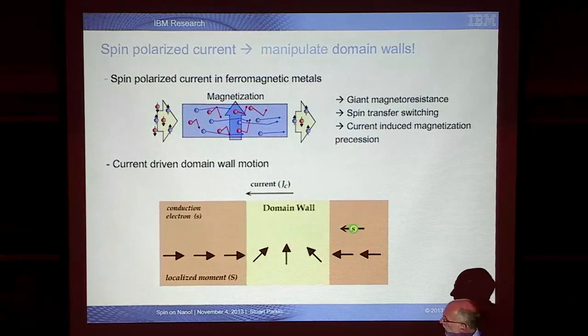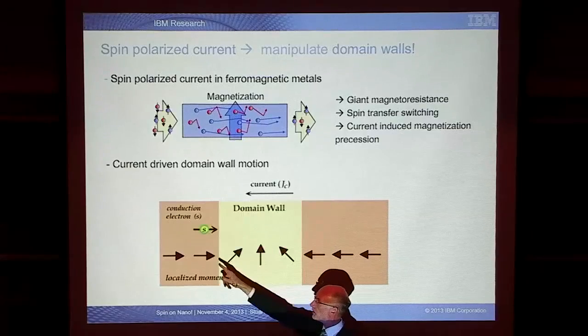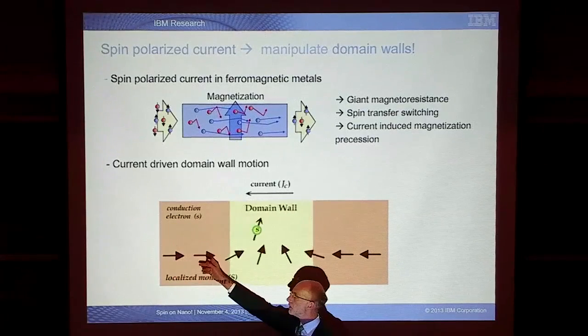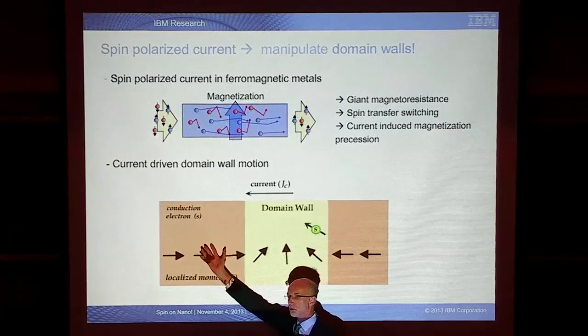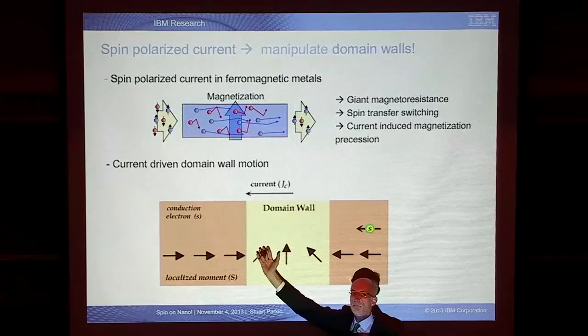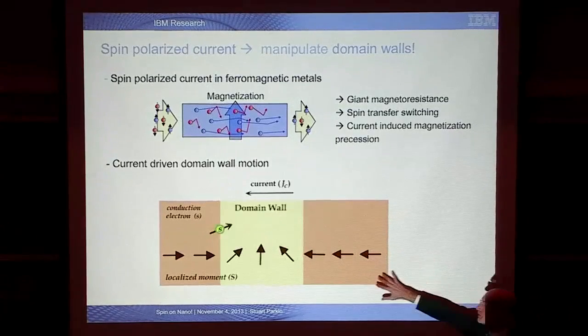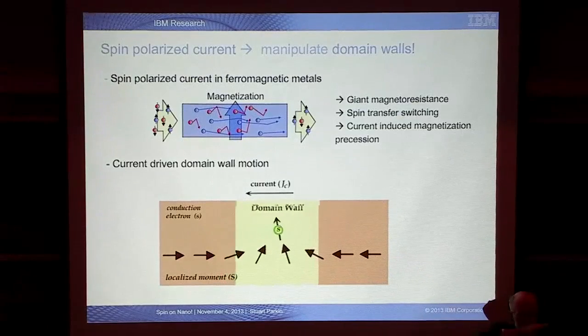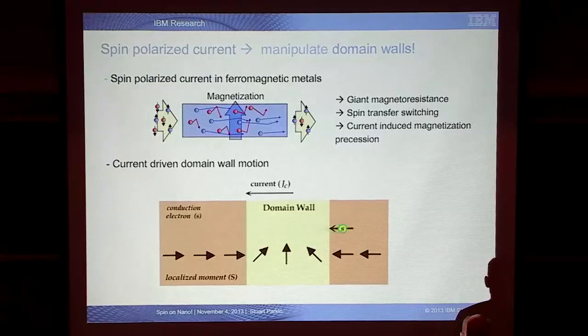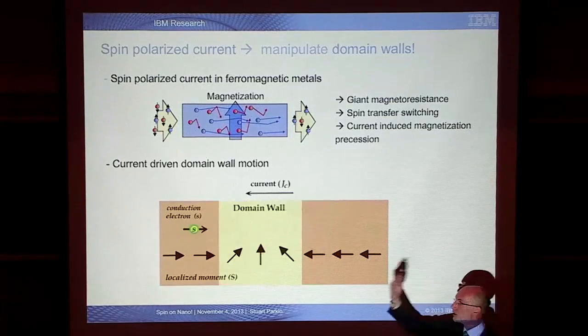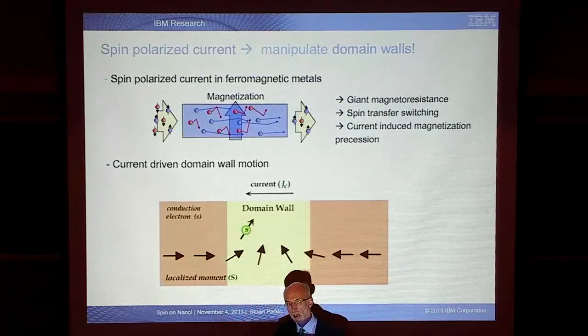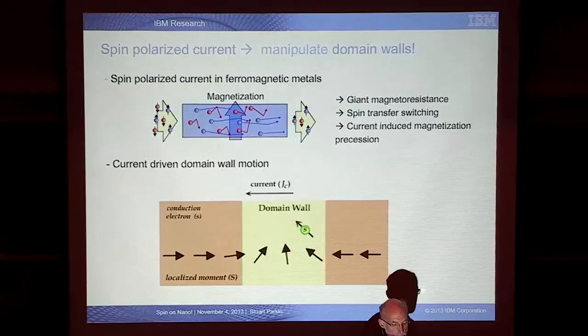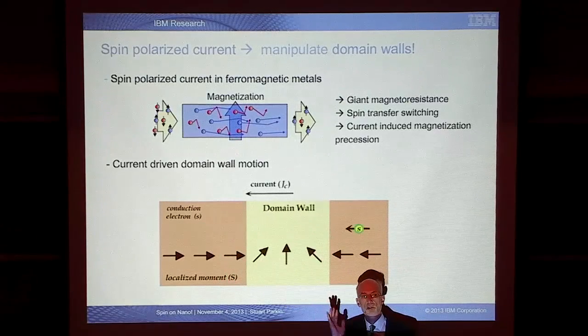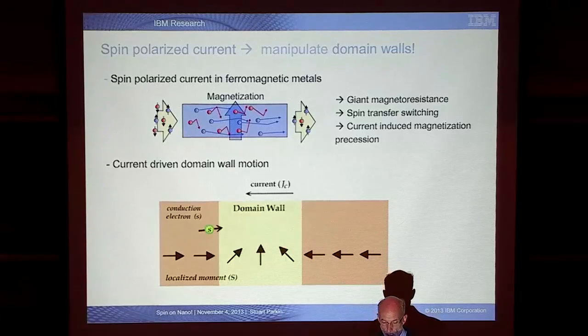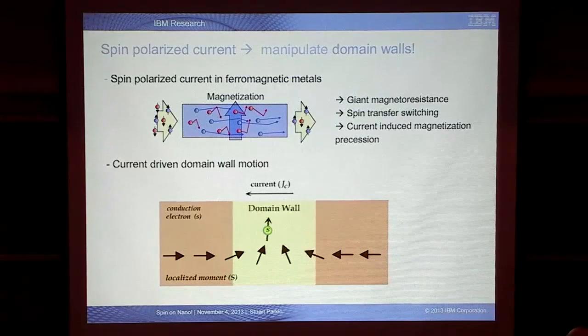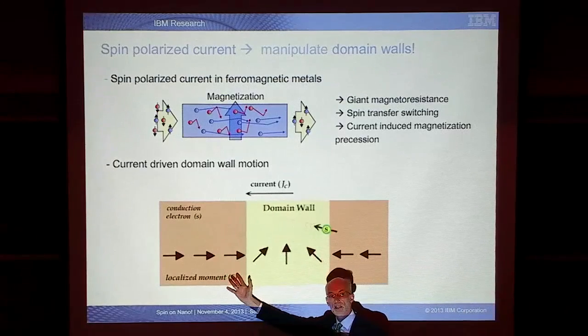It has momentum. More importantly, though, now if we pass a current through this wire, you see these electrons, their spins will be parallel to this local magnetic moment direction. And when this electron crosses this domain wall, you'll see adiabatically its spin will rotate to be parallel to the magnetization of the opposite magnetic region. As the electron spin rotates, it delivers a quantum of spin angular momentum to this magnetic system. And in response, a local magnetic moment rotates. For each electron that is spin polarized that passes the domain wall, a single magnetic atom will rotate its moment direction to preserve in totality the angular momentum of the system. So if we pass enough electrons, enough of these moments will be rotated that the domain wall will move.